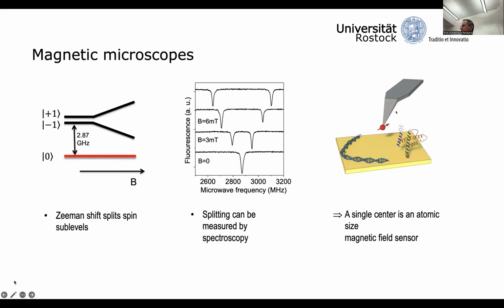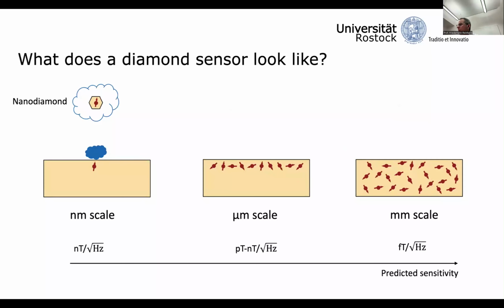And with that, we can dream of experiments like this, where we attach one of these defects to the tip of a scanning probe microscope, we scan it across the surface, and we measure, for example, the magnetic field of single biomolecules. This has sparked dreams, and many experiments have been performed in many different approaches. They essentially can be distinguished in two classes. One is to use single nitrogen vacancy centers to perform experiments with moderate field sensitivity, nanotesla per root hertz. This is only barely better than the magnetic field sensor in your smartphone. However, it's obtained by a sensor which consists of essentially a single atom.